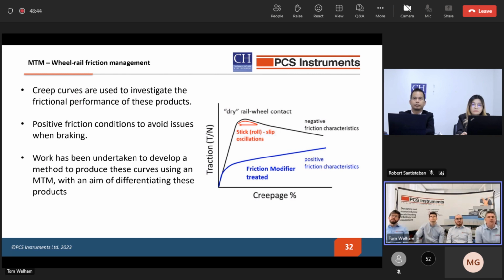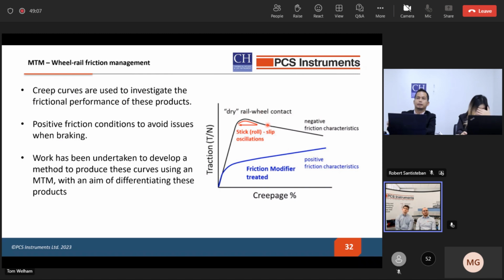There's a phenomenon in trains which you can hear, the screeching as trains go around corners or when braking, and that's a stick slip system that I've tried to illustrate here. They use the term creepage, which is the same as slide roll ratio, but if we have a certain amount of sliding, we have this unstable system where we come over this hump and keep oscillating between different levels of sliding in the contact, and that oscillation is the screeching that you can hear.